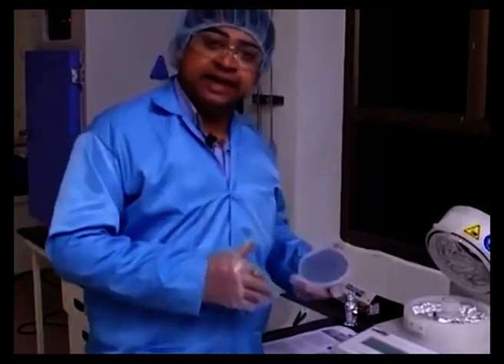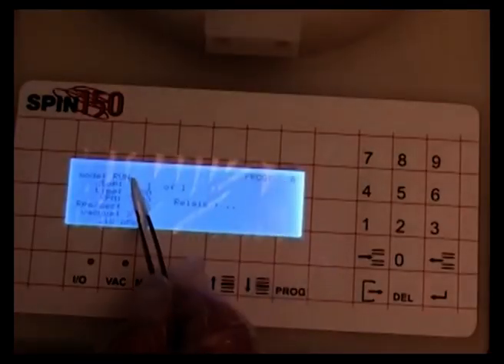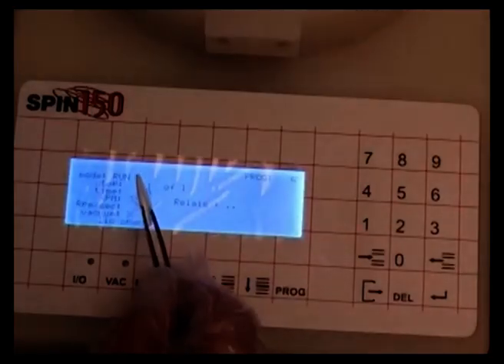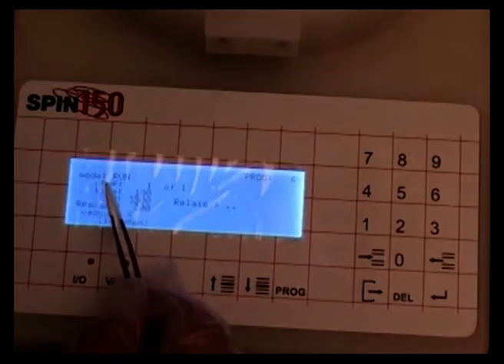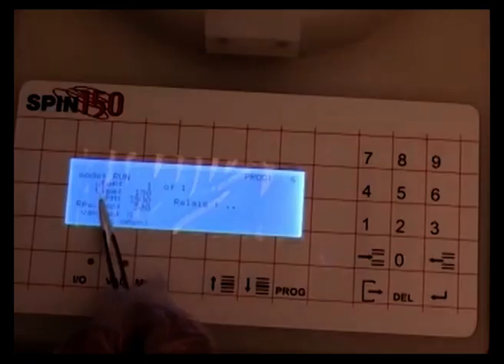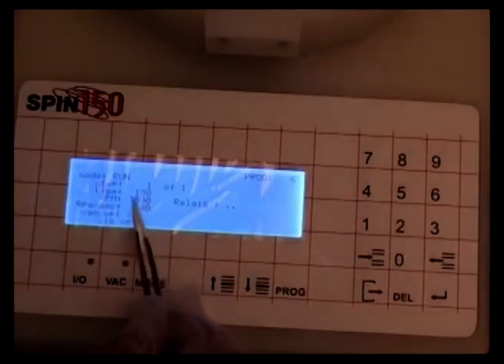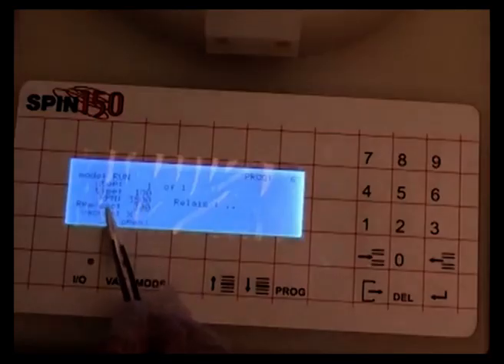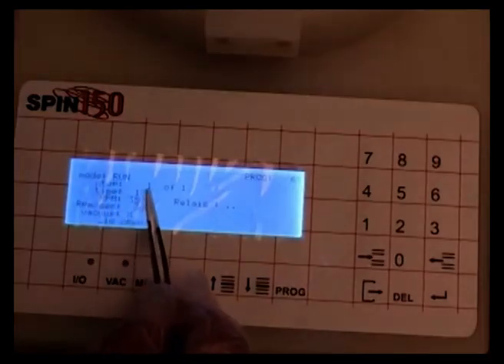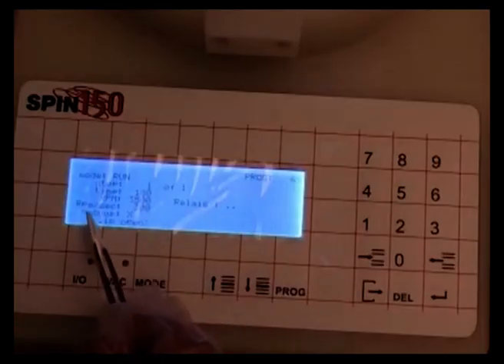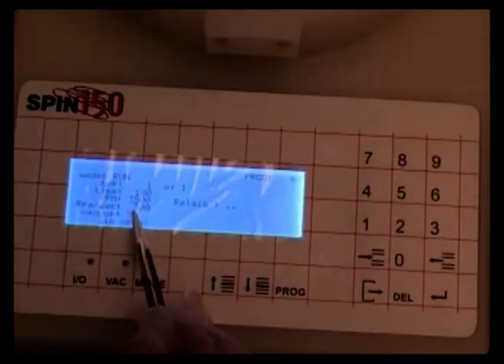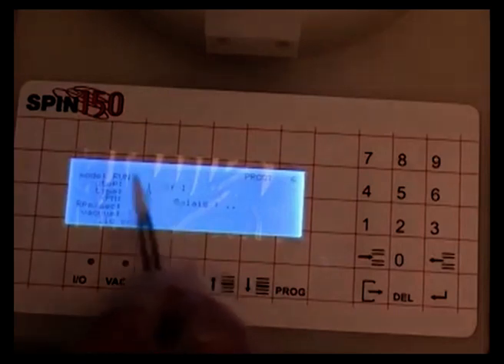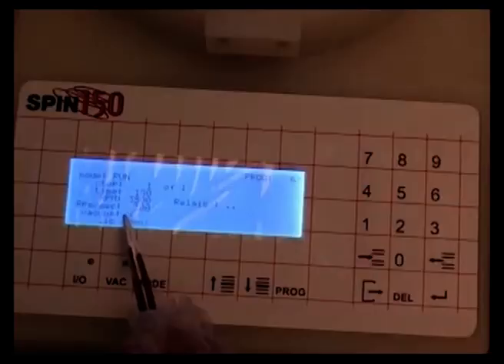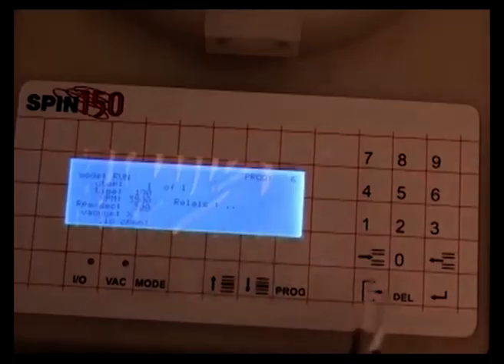So let's look at that in our next step. Corresponding to this program number, what all steps are there in the program are illustrated just in this particular region. As you are seeing here in the run mode, step 1 of the program illustrates that there would be an RPM of 3500, attained at an acceleration of 300 RPM per second, and the hold time for this is about 180 seconds, with the vacuum option on so that the wafer is pulled down while the spinning happens. Finally, you have to change this program to suit your requirements.